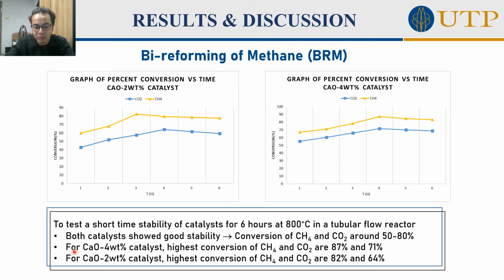And for the CaO 4% catalyst, the highest conversion of methane is 87%, which is here. And for the CO2 is 71%, which is here at the 4 hours. And for the 2% CaO catalyst, the highest conversion of methane is 82%, which is at the 3 hours. And the CO2 conversion at the highest is 64%, which is at the 4th hour.